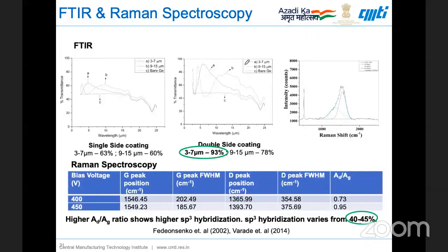For transmission studies, we coat diamond-like carbon on a germanium wafer, which is typically used for night vision applications and night vision camera lenses. A bare germanium wafer has about 47% transmission. When you coat it with diamond-like carbon, it can transmit up to about 90 to 93%, and this is what we have done.